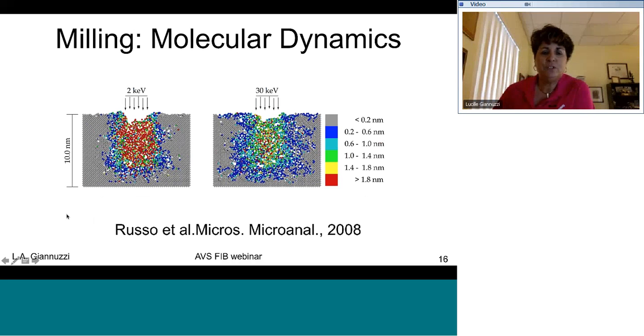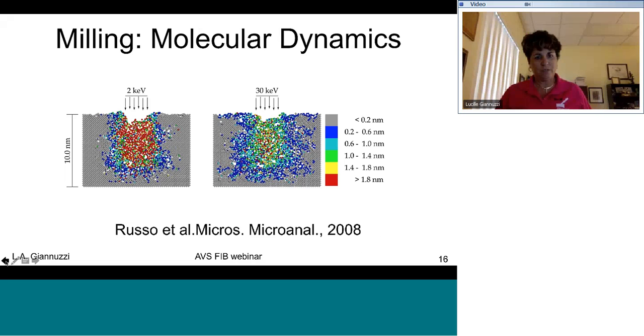Here's some work I did a few years ago with Barbara Garrison and others at FEI when I was there. This is a molecular dynamics simulation showing the ion mixing at 2 kV and also 30 kV. To me, what's interesting about this is that if you can get a monochromated 2 kV beam, you'll have less ion mixing than with the 30 kV beam. You'll actually get a lot less damage and a lot tighter beam spot, although the sputtering is a little bit less. But you can probably get some interesting results from a monochromated 2 kV beam, which of course doesn't exist yet. But that's on my wish list for the ion beam folks to develop.